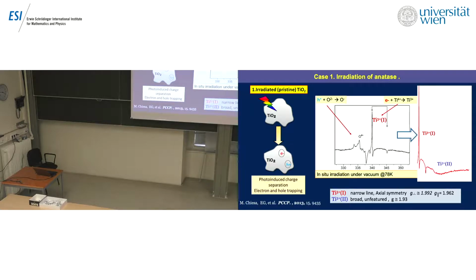You can see that this is something that EPR people don't like, because the signal is broad and featureless, but it represents the majority of the electrons in the system, because the intensity of the number of spins in the system is proportional to the line width and to the square of the line width. So it means that we have few electrons of type 1 and many electrons of type 2. I am also interested to show you where the polarons go, that this is interesting in a real system, okay?